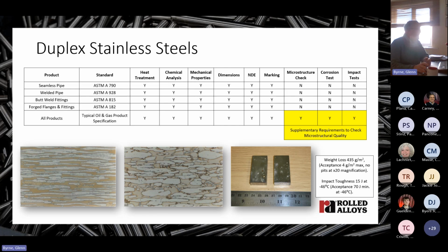This is an example here where we show two corrosion test coupons that have been exposed to ferric chloride solution at 50 degrees C for 24 hours. Now, the acceptance level for that test is a weight loss not exceeding 4 grams per meter squared, and there should be no visible pits at ×20 magnification. Well, the pit in here is clearly visible and gross, and the weight loss that we measured was 435 grams per meter squared, and that's as a consequence of sigma in the microstructure.